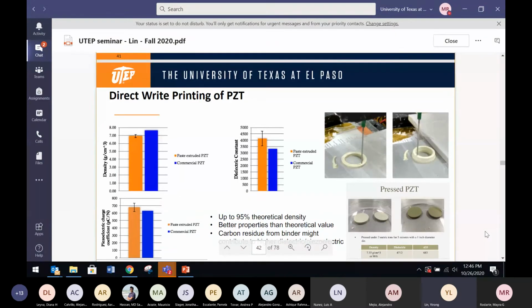All right, so this one here is just to show you, again, we want to print PZT, which is the most useful piezoelectric ceramic, right? So what we're seeing here is we can achieve about 95% of theoretical density, which is very good, right? We achieve piezoelectric and dielectric properties that are even better than commercial values because of the carbon residues, right? Basically, once you do slurry printing, sometimes these carbon residues after sintering are not good for you, but in this case, it's better because it forms a lot of local small microcapacitors to increase the dielectric and piezoelectric properties.